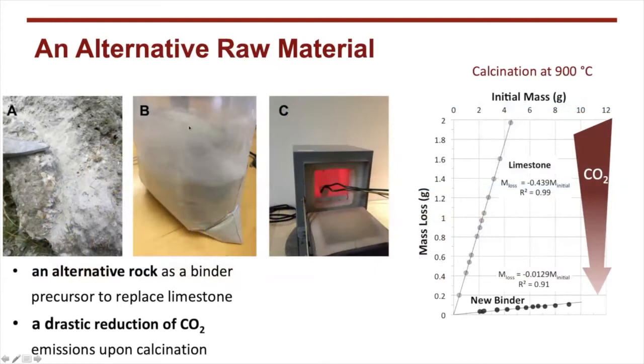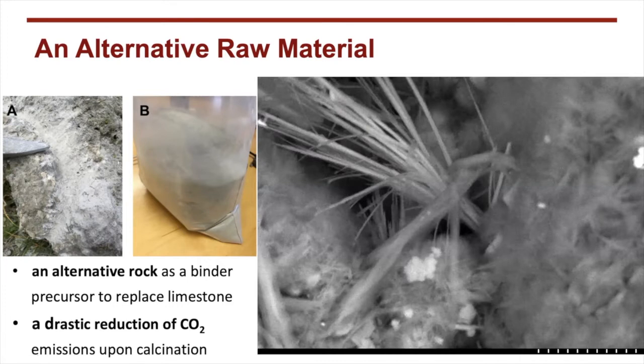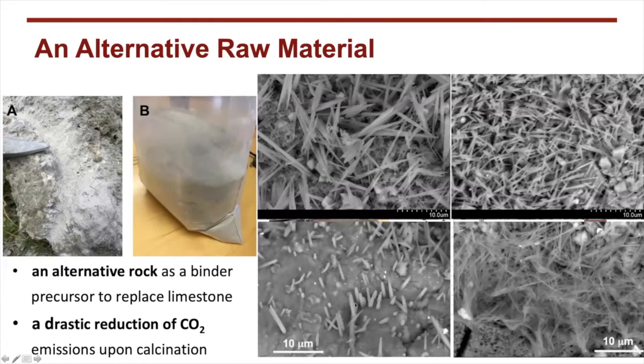So we are using an alternative binder precursor, so basically a new rock that replaces limestone. The plot here shows the mass loss that the new binder precursors experience upon calcination. You can consider the mass loss as a proxy for the amount of CO2 emitted upon calcination. And for comparison here, I'm showing the data from limestone. So the difference, which is given by the two slopes, is striking. At the same time, we are also studying how to grow mineral fibers within the binder. You can see here that fibers are literally sprouting from the paste as if it were a living creature.